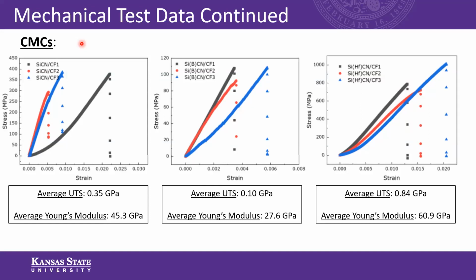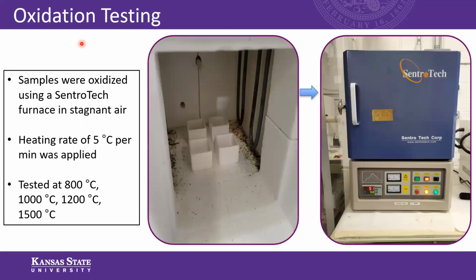So as you may have noticed, these values are much lower than the uncoated carbon fiber counterparts. However, this type of effect is expected, as during the fabrication process, the CMC has some weakened effects in its mechanical abilities. So now moving on to the oxidation testing. Oxidation tests were done in a Centrotech box furnace, and they were conducted in standard air and were heated at a rate of 5 degrees Celsius per minute. They were tested at 800, 1000, 1200, and 1500 degrees Celsius.